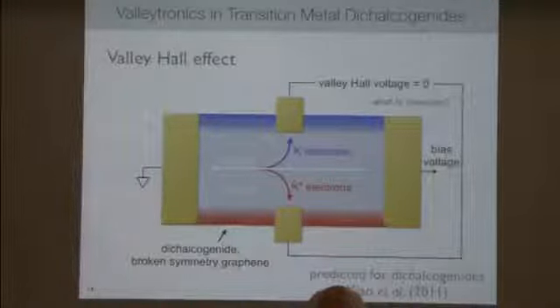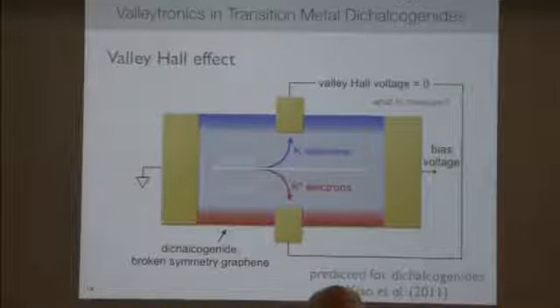So by analogy to that, it was proposed very recently that there could be a valley-based Hall effect, the Valley Hall effect. And the idea is simply that, similar to the spin Hall effect, because of the different momenta of those two valleys, electrons in the K valley, for example, will drift to the top of the sample, and electrons in the K prime valley will drift to the bottom of the sample. And so there will be populations of just one valley on either side. But because there's no difference in charge between these two valleys, there's no voltage to measure. So one question is, what do you measure in this case?